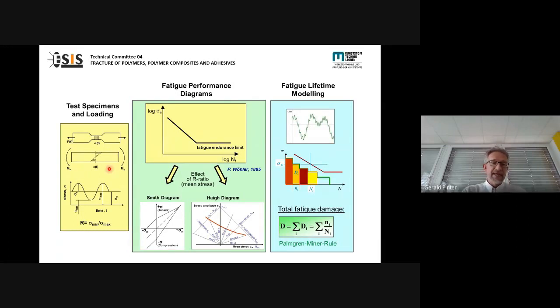or what else. We load the specimen in a fatigue load, in this case a sinusoidal load with a maximum load, a minimum load, and the stress amplitude. And what we typically measure in conventional fatigue tests in materials and in polymers, that is the so-called Wöhler lines, the S-N curves, where we measure the cycle numbers to failure at different stress levels, at different amplitudes.